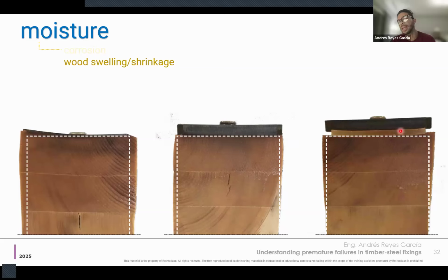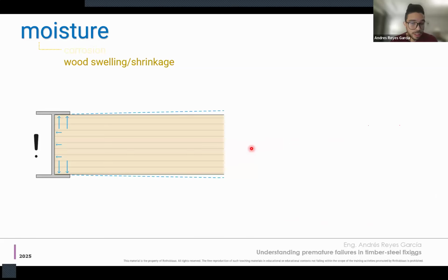We also tried with a damping element. You see here, this is an acoustic profile, a soundproofing profile, and it has a very positive effect. We're not going to talk about this, but this is just to show the effect of swelling and shrinkage. And this is very limited also to one screw, one thick metal plate that is pretty much the size of the wood sample also. So we think that this is not even the worst case scenario for wood swelling. We are not considering also the binding effect. This can make it potentially worse, and this has to be researched.